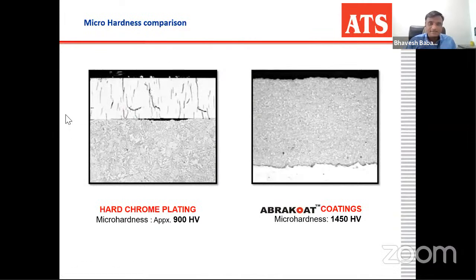If you see the microstructure of the chrome plated and the Abrakoat process: in chrome plated, there is no bonding layer. This is the base material, this is the chrome plating. In chrome plating, there are many micro cracks, so it can very easily peel off from the base material. But here, you can see the Abrakoat microstructure is 100% penetrated with the base material and there is not a single micro crack. So we get a good life. There is no chance of the coating peeling off from the base material, so we run our roll for a much longer time without any quality deterioration.